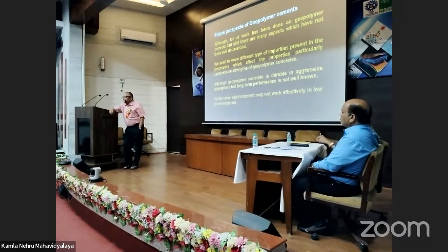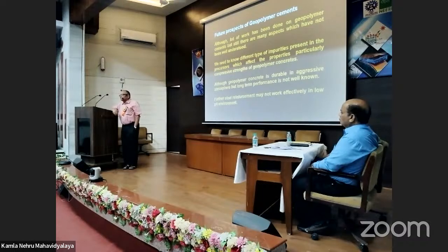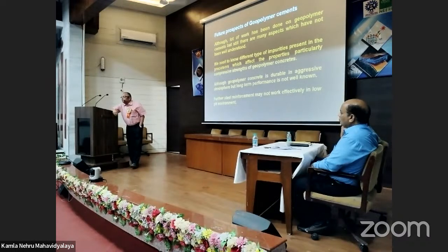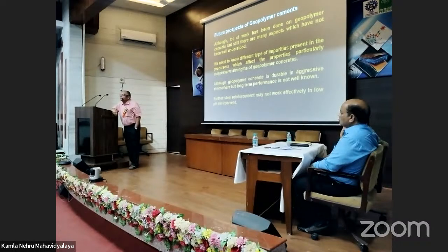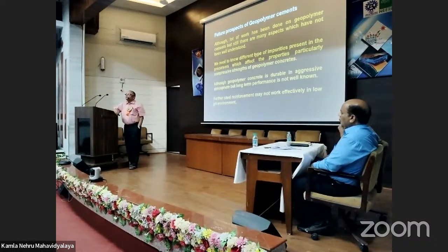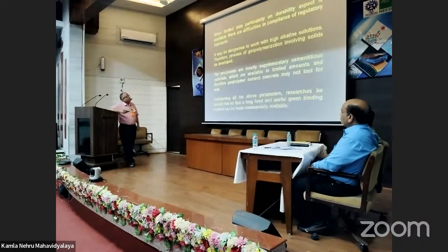And in lower pH range, the corrosion is much higher as compared to ordinary Portland cement. Because if you add water to Portland cement, the pH may go up to 14, and somewhere it is reported it may even be 14.1, 14.2. Of course, it is theoretically not possible, but it reaches up to 14. But if you have sodium hydroxide, it will have 10 or 11 or 12 pH, and if you increase the concentration, there may be other types of problem.